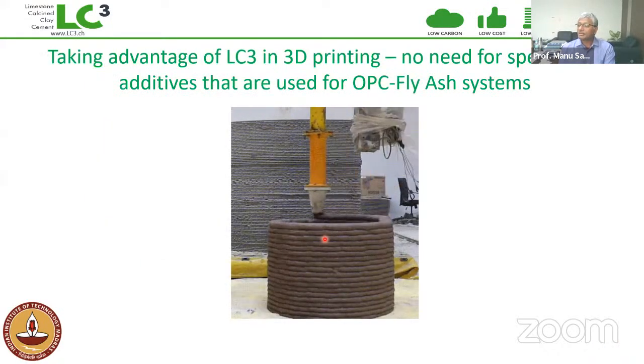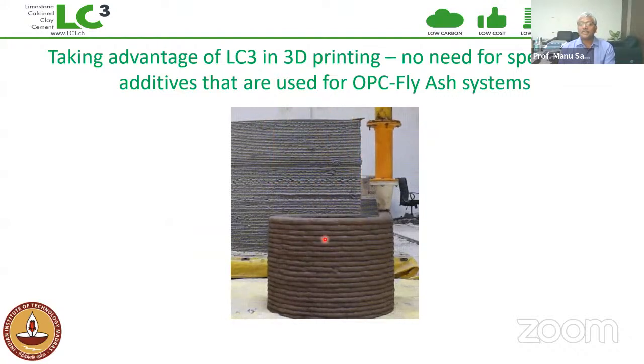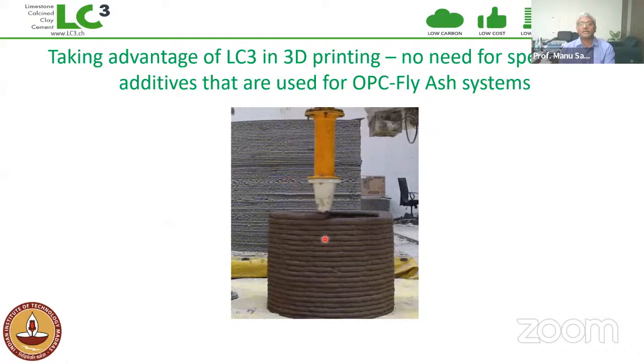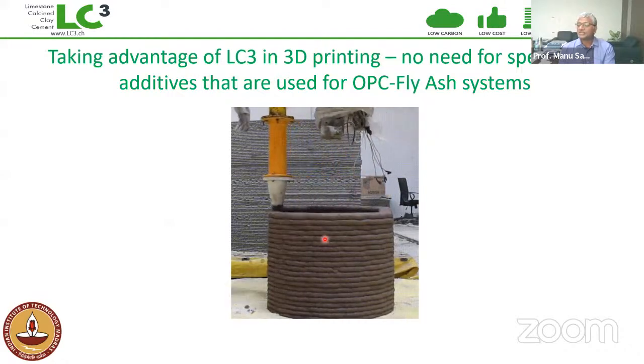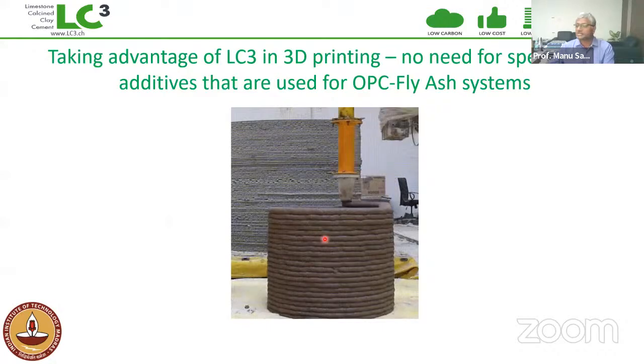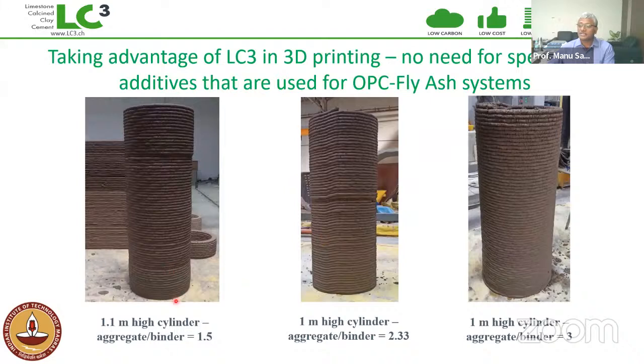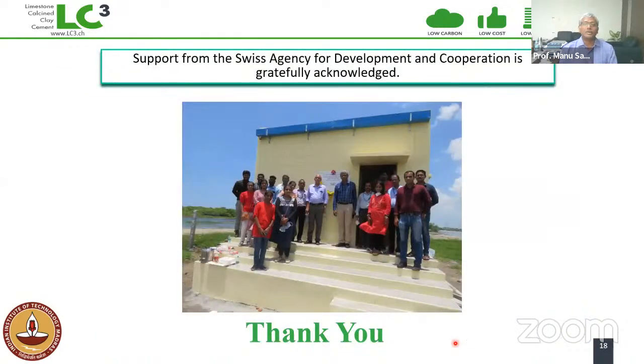As you can see, the concrete with LC3 can be printed fairly quickly without really stopping, and it provides an excellent buildable mix, which is able to produce 1 meter tall columns in 20 minutes. And that's what we had done with LC3 and 3D printing here. You can see with LC3, we are also able to increase the aggregate amount in the concrete which is being 3D printed. So that's a very big positive with LC3-based systems. So again, this is just an additional example of where LC3 can be applied, but primarily we are obviously concentrating on looking at LC3 in chloride-related environments. That's where the most potential with LC3 can be derived.